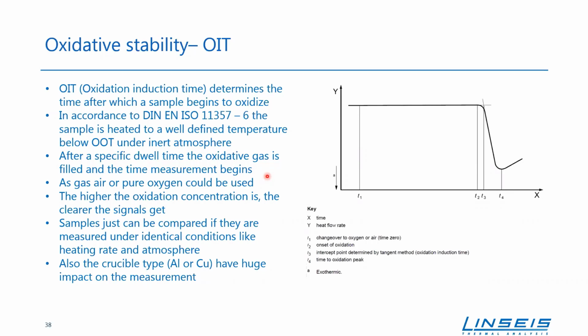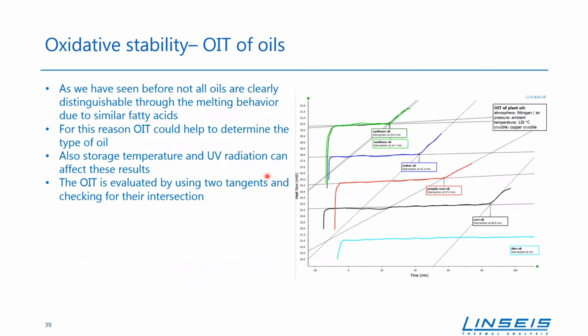And what we've also used is the copper crucible here. So our example in this case are the oils again. First of all, we compared two sunflower oils, and what we can see there is the onset for our oxidation induction time is really the same. So after 24.2 or 24.7 minutes, the oxidation starts. In comparison to the others like walnut oil or corn oil, there's a huge difference, and the reproducibility is quite good here in this case.